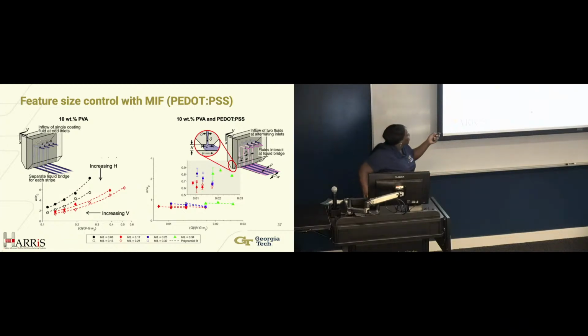So again, this is showing more of the same, where we have, again, a single fluid that's coated, and whenever you increase H with increasing V, you can see there's a shift, a wide range. Whereas here, again, no effect. So we know that we're onto something very, very interesting, and we can begin to create and tune our structures to what we want them to be. And we can determine how wide each of those features are.